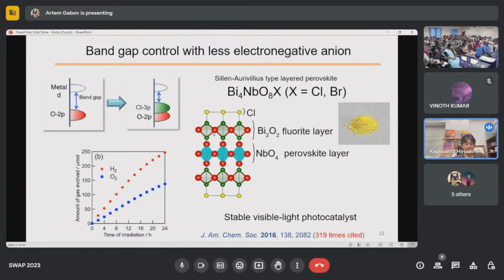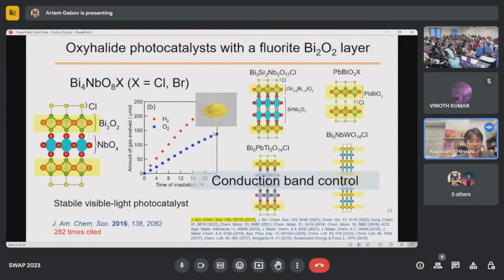And this is actually possible with this bismuth niobium or tantalum oxyhalide material we reported 7 years ago. You see that this yellow color shows the reduced band gap. And actually, this shows a very stable visible-light photocatalyst. The problem of mixed anion compounds is usually instability against photo-generated holes. But somehow this material is very stable against the photocatalytic reactions. From the structure point of view, the most important part is this Bi2O2 layer, which acts as an important unit for catalytic activity.